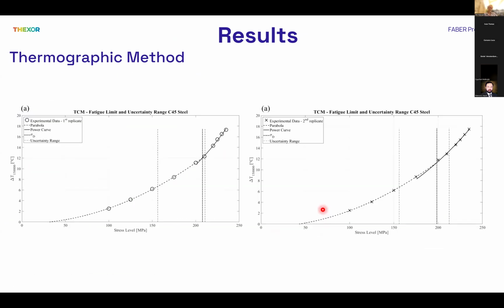This slide explains very quickly how the thermographic method, the two-curve method routine, works. On the left side are the results from the first experimental campaign, and on the right side the results for the second experimental campaign, referring the approximating curves to the parabola and power law approximating curves. This vertical line is the intersection of the two different approximating curves. The dashed lines refer to the parabola mathematical formulation adopted for the thermal parameter approximation below the fatigue limit, while the solid line refers to the power curve mathematical formulation adopted for the thermal parameter evolution above the fatigue limit.